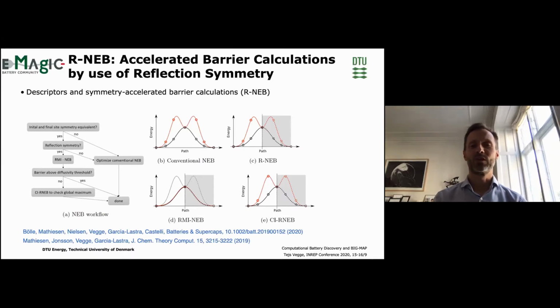If it is sufficiently low, we calculate only the symmetric half of the barrier to get a better estimate of the barrier for the transport. If it is completely asymmetric, we calculate the full barrier. This allows us to accelerate the kinetic analysis by a factor of 5.